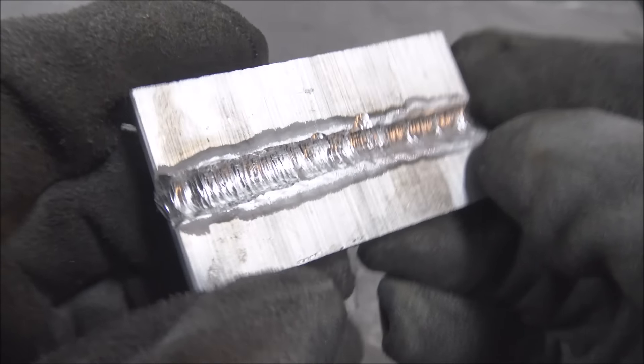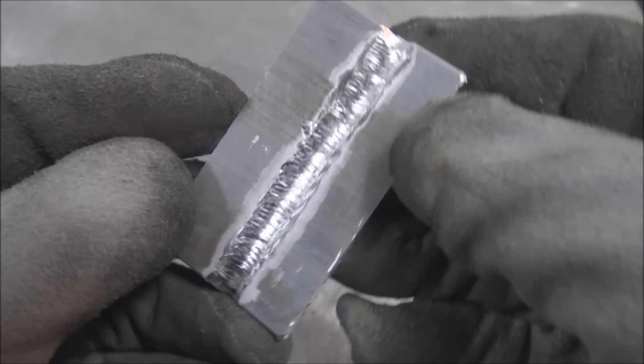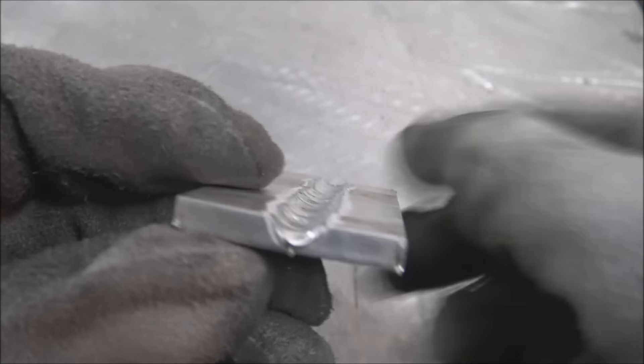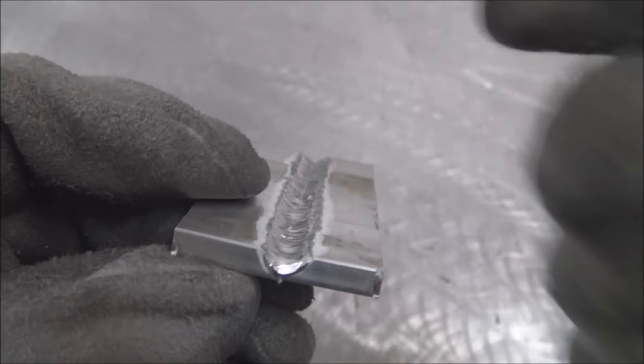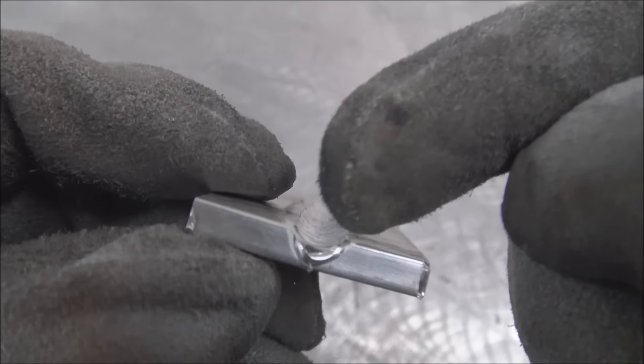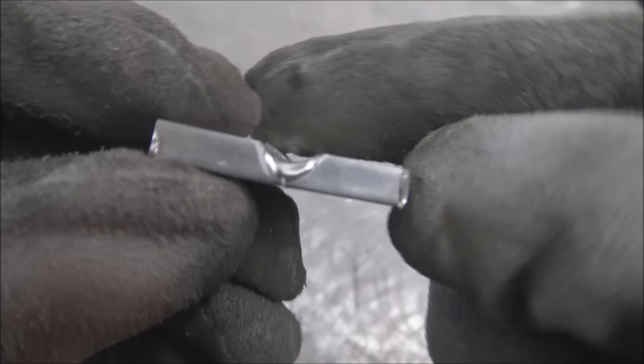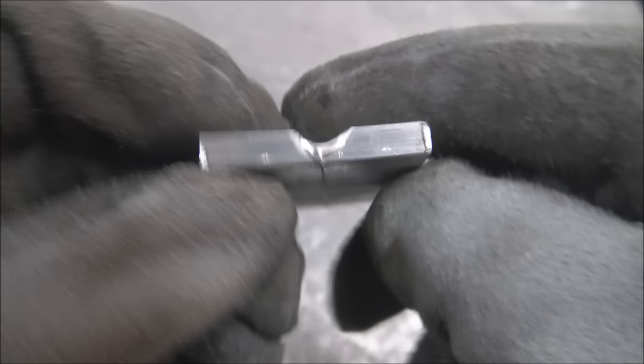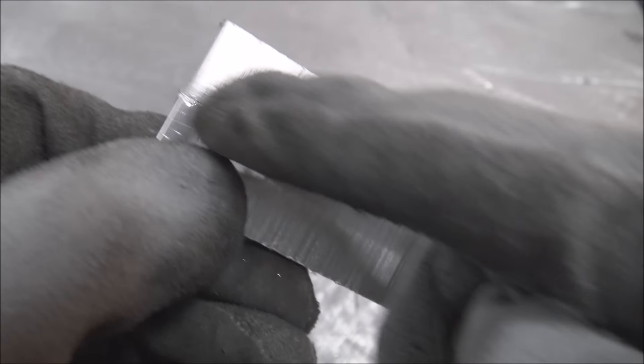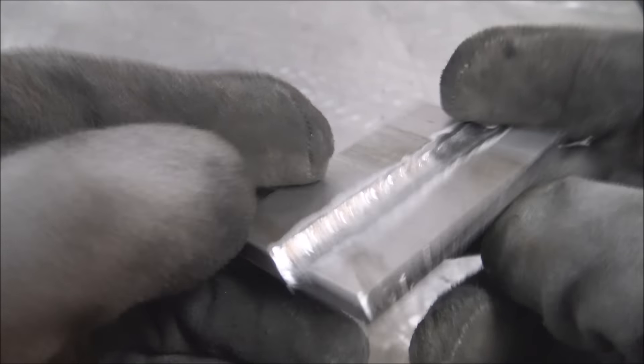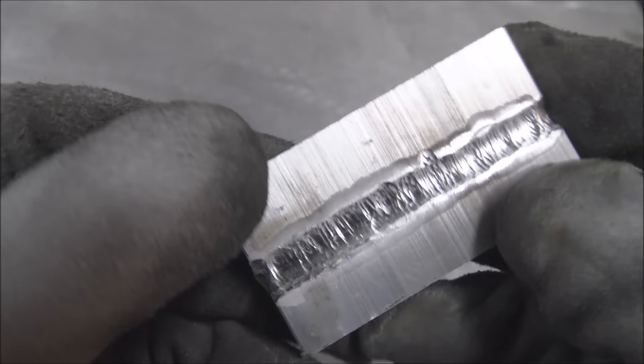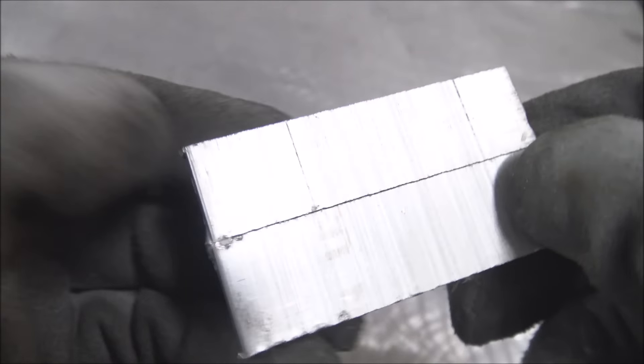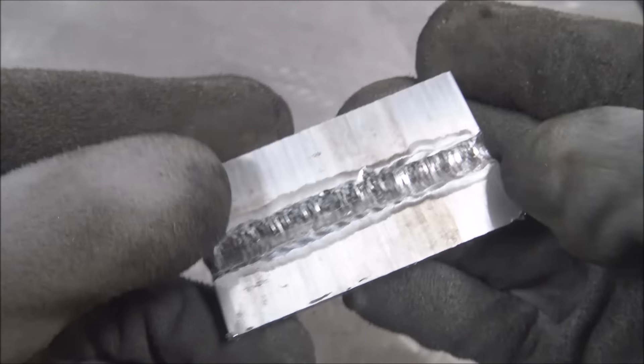And then like almost everything else, it always depends on what you're doing, what you're trying to achieve. So there are several ways to do this. You can grind through about halfway like I did. Run one or two passes, whatever you need to get this capped up higher. Flip it over and then grind back into your weld. Open this back side up and weld it. Or if you're not needing it super strong, you can just weld in here and call it good and just have a gap back here. Like I said, it depends on what you're building.